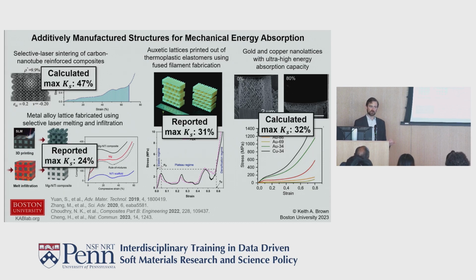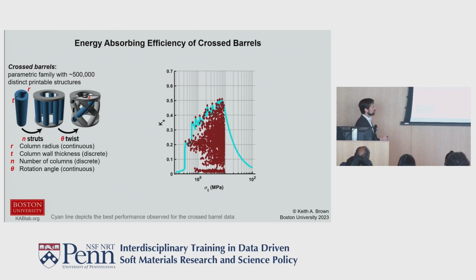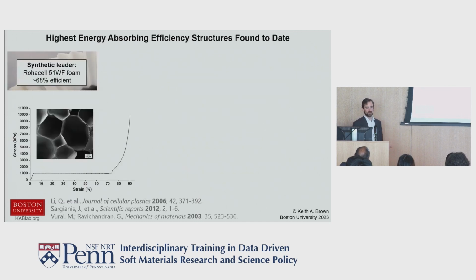But let's also look a bit inwardly. I showed you 3,000 experiments before. How did we do? Well, these are all the cross barrels I studied. Here we have this metric Ks, and I'm looking at the range of the different efficiencies across the different stress values they can obtain. And you can see that it tops out at around 51%. So, okay, we did slightly better. But is there room to go from this? So we looked for examples of materials that are much better than this. Well, the best synthetic material we found is a foam you can purchase called Rohacell, which is about 68% efficient.